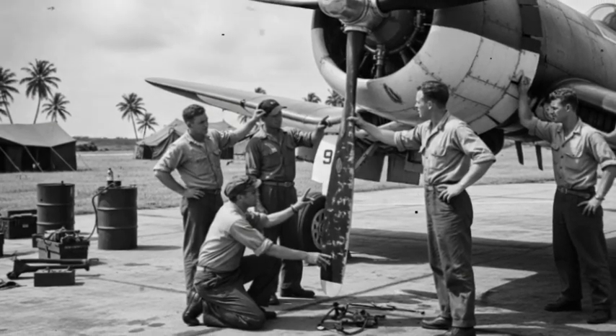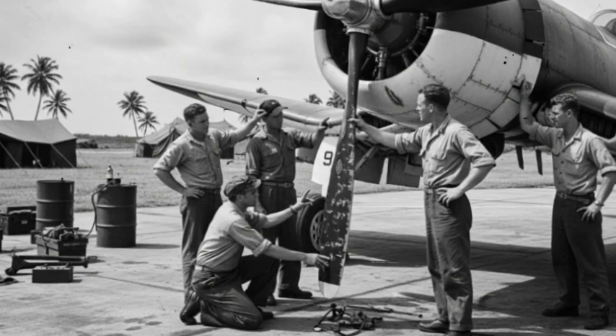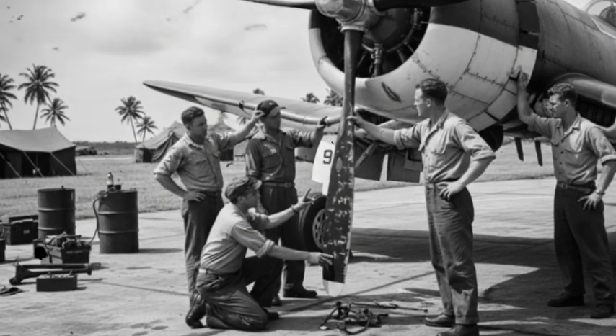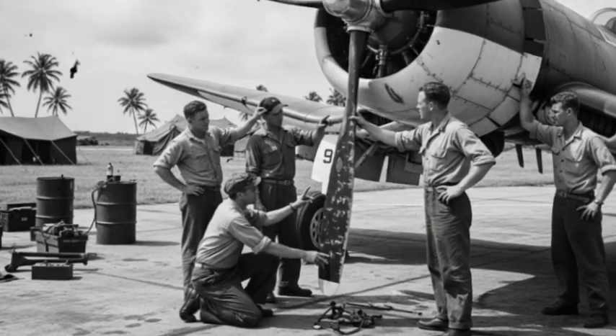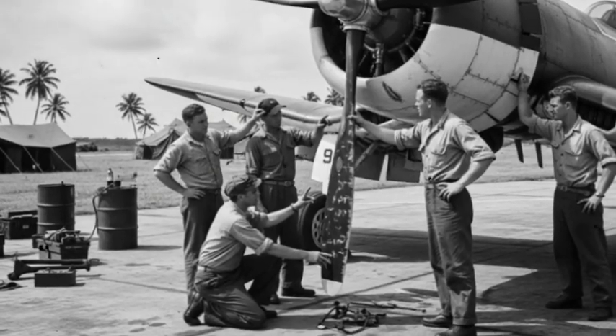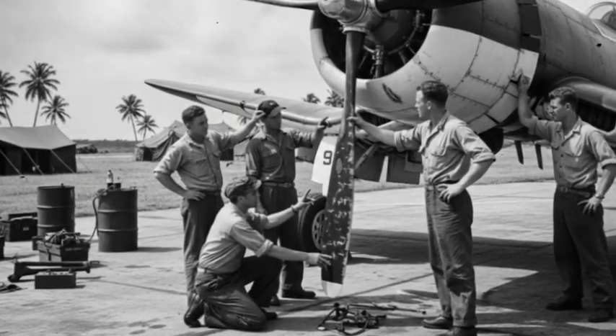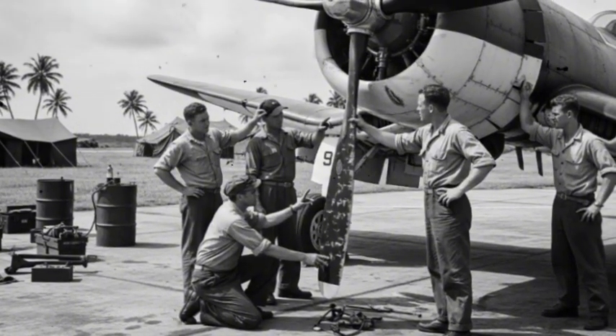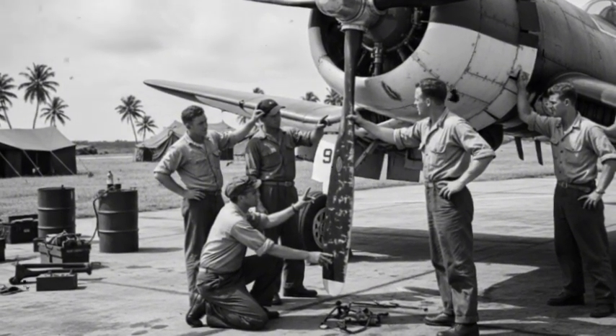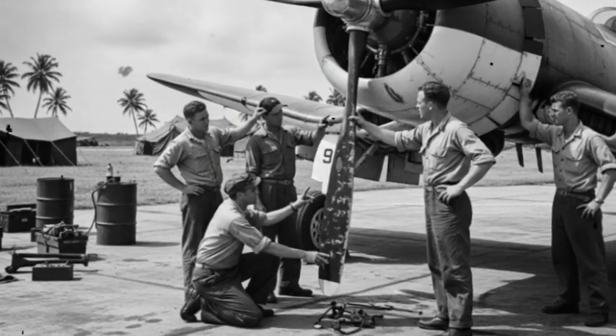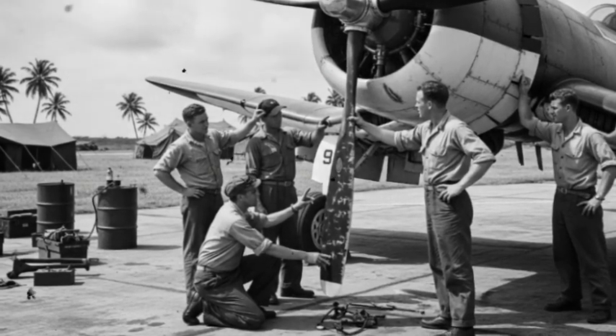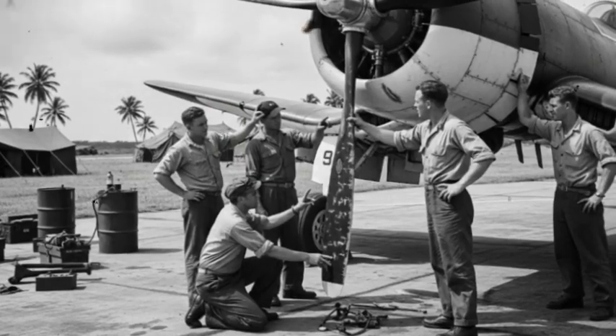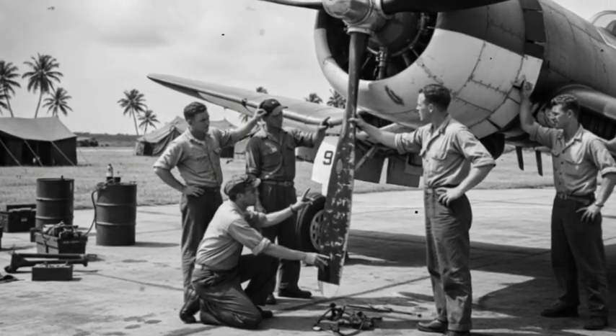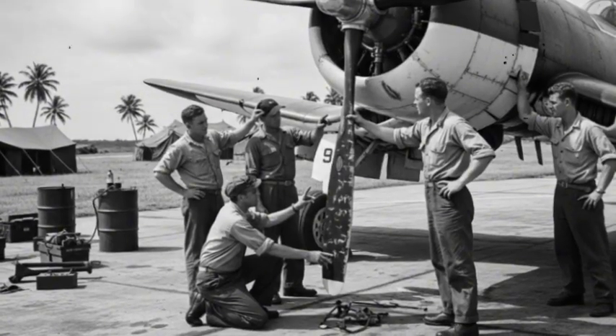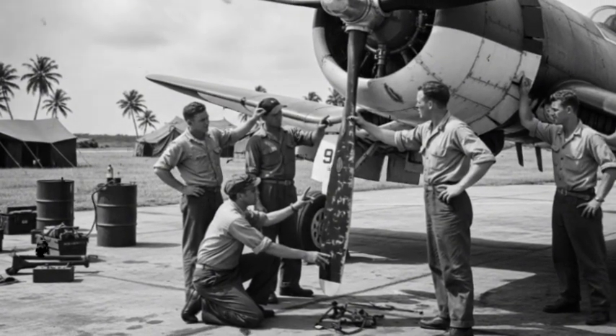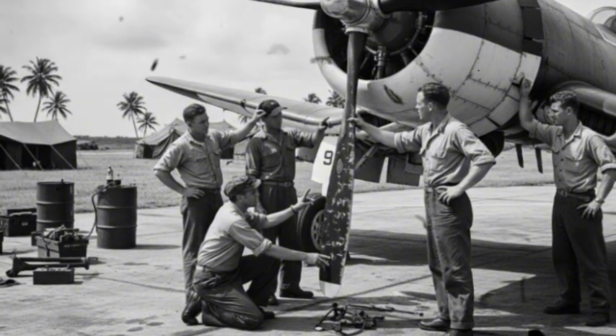The standard propeller specification called for an aluminum alloy designated 24ST, a copper-aluminum composition developed by Alcoa that offered excellent strength-to-weight ratios and predictable failure characteristics. When stressed beyond design limits, 24ST alloy would crack in controlled patterns that allowed pilots warning time before catastrophic failure. This predictability was considered a safety feature. Better to have a propeller that gave notice of impending failure than one that disintegrated without warning at combat power settings. But the Pacific Theater was revealing problems that laboratory testing had not anticipated.